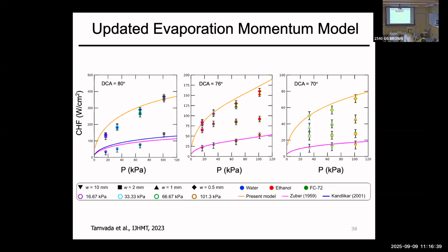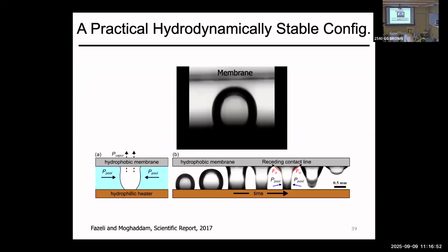So the hypothesis was examined by looking at those experiments. If you take the right model and don't try to force it to the experimental results, but use experimental results collected in the right regime, then you can see that you can predict it. Kandlikar's model assumes an infinitely long, cylindrical geometry, and that geometry gave that factor of 4 difference and allowed it to fit into the existing data. So you might ask, well, I'm not convinced.